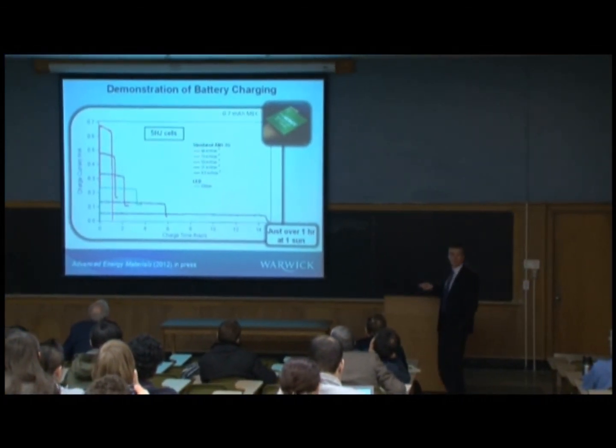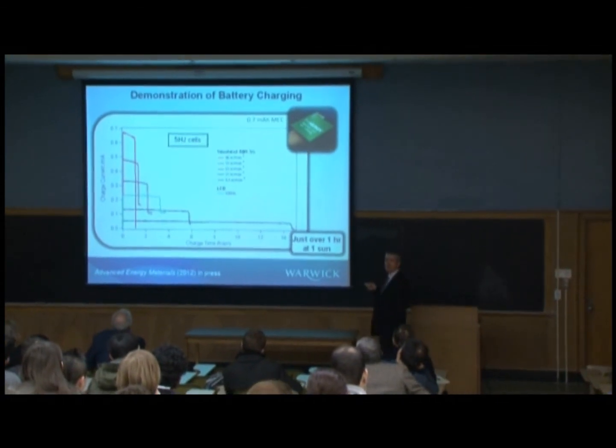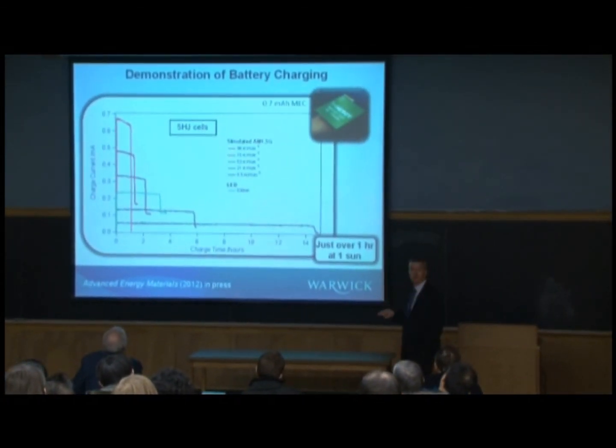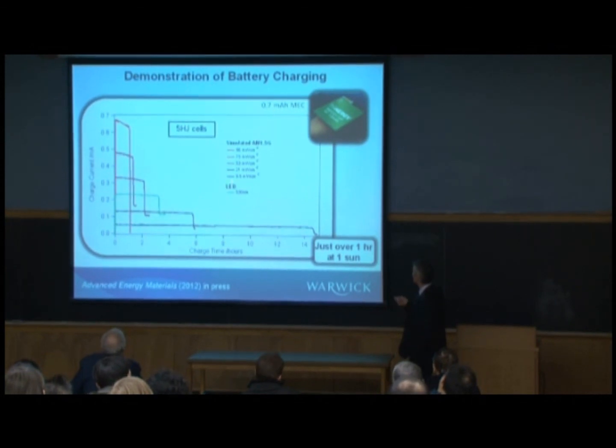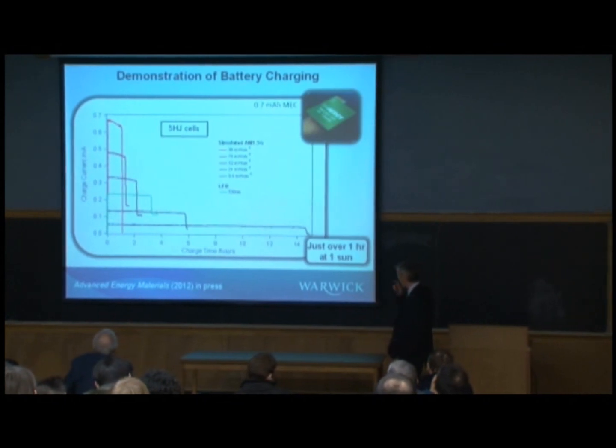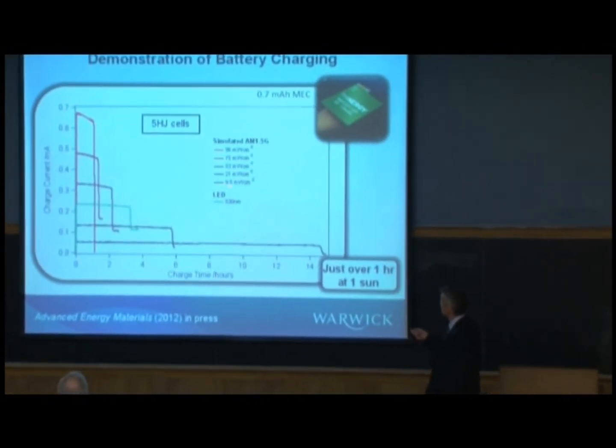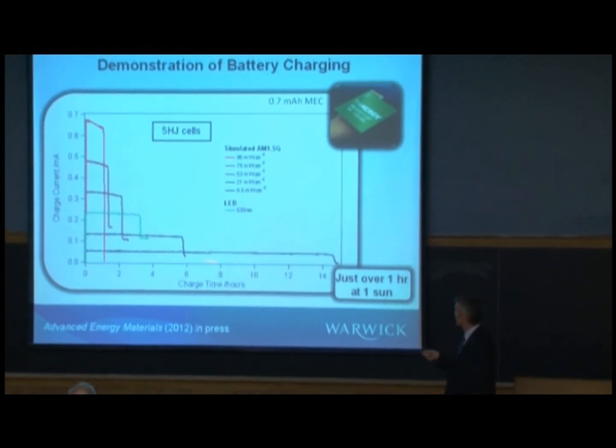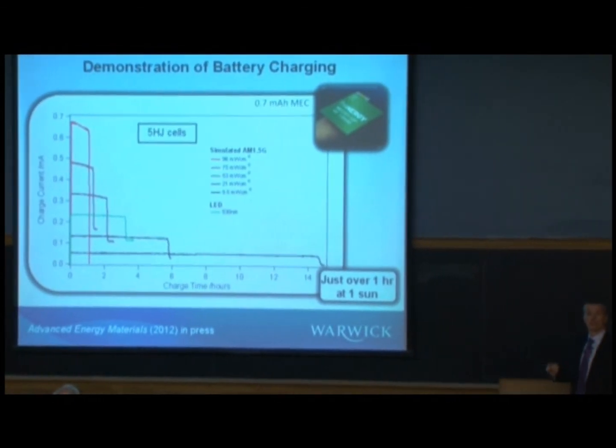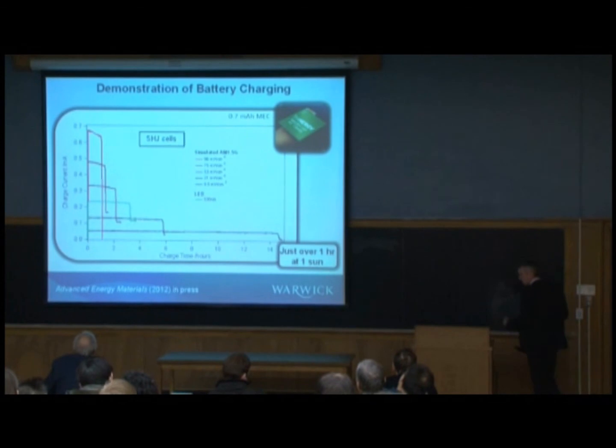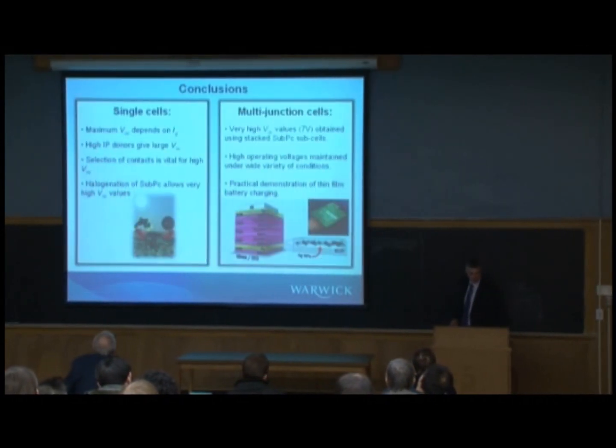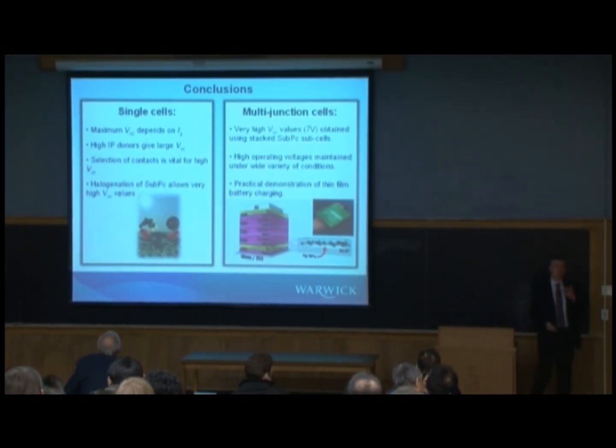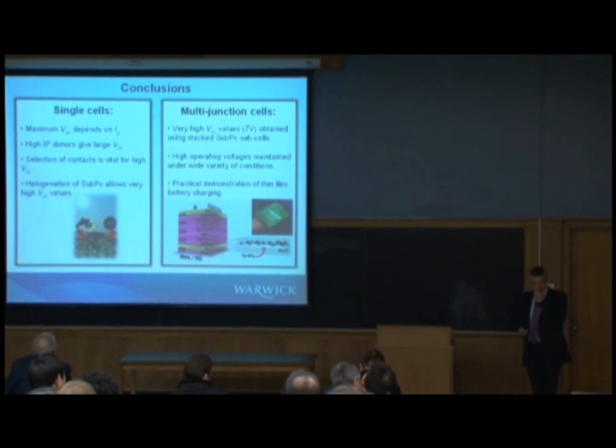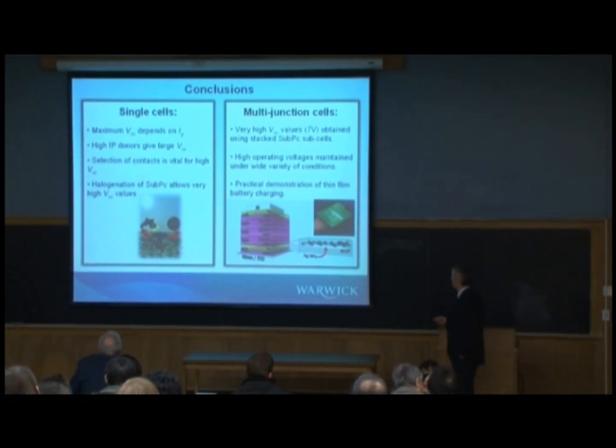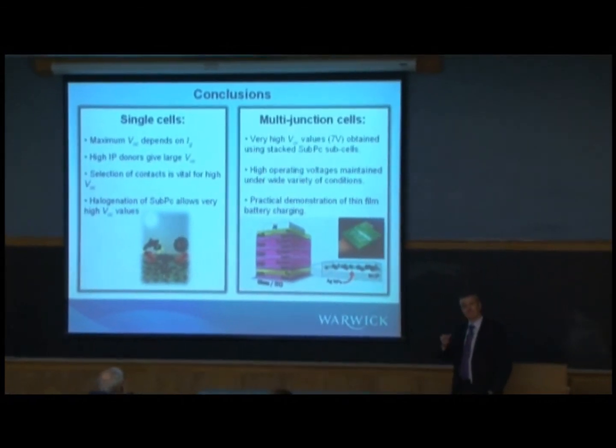Whereas if you drop the power, you go cloudier and cloudier in effect, then obviously it takes longer and longer to charge. But even using an LED, green light, 530, it only takes 3 hours? And obviously lots and lots of hours as you drop down to about 10 milliwatts per square centimeter, but 12, 14 hours, you'll still get that charging, because that voltage is maintained. So we think that's quite a nice illustration of how you can use these cells for doing something practical, charging something for consumer electronics.